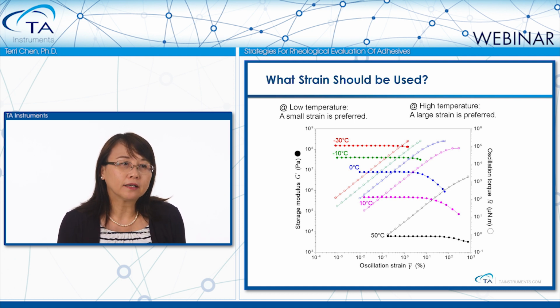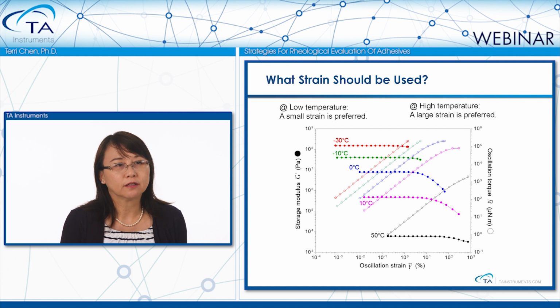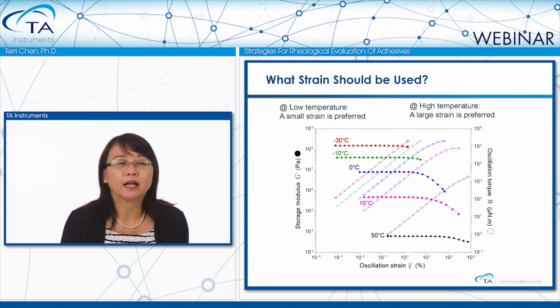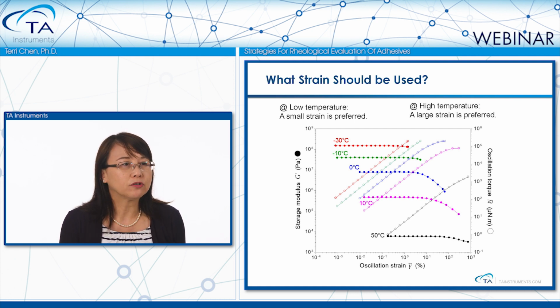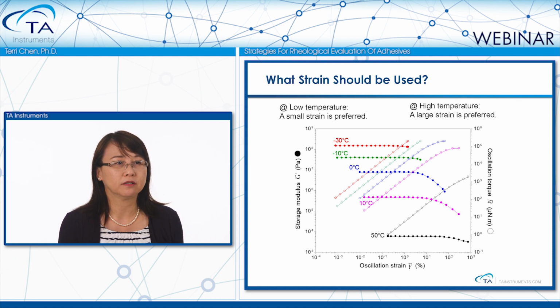Then let's look at the black curve on the bottom of this figure. This is the strain sweep experiment at 50 degrees C, which is above the glass transition. At this temperature, the sample is really soft and has low modulus. A 1% strain will get a torque of less than 10 micronewton-meter.